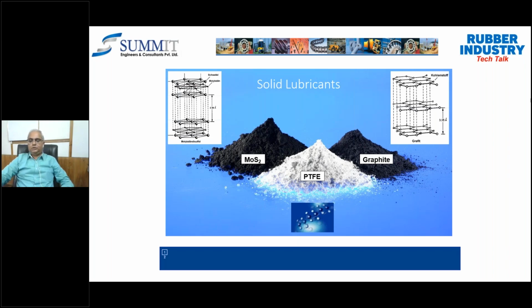So it has got a low friction achieved as a crystal structure shears along the layer boundaries actually, and that's very important actually. Whereas for the PTFE, a low friction coefficient is particularly effective in the plastic lubrications actually. Molybdenum disulfide is again utilized, and it is very good where the high temperatures are very important actually. So looking into such kind of things, when I want to go for the 500 plus degree centigrade temperature, I can think of using the graphite.